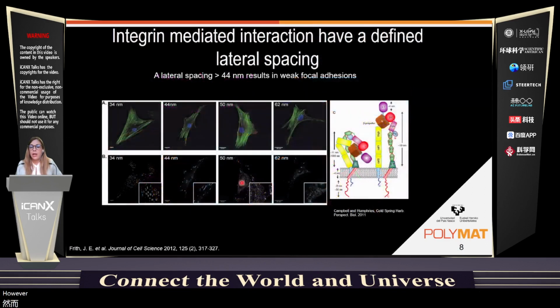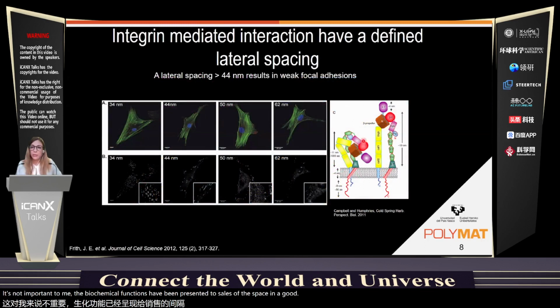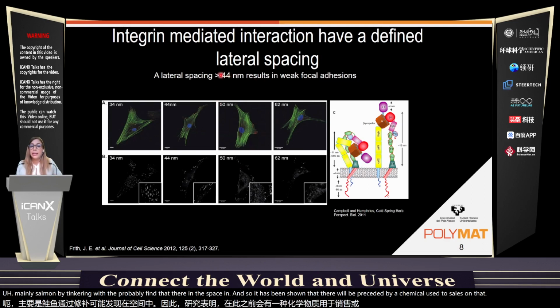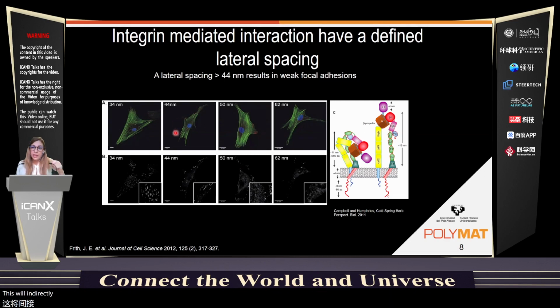However, here it's not only the biochemical functions that we present to cells that are important, but the spacing at which we do it. So these are mainly sensed by integrins that have a defined lateral spacing. And so it has been shown that if we present biochemical cues to cells at a lateral spacing lower than 44 nanometers, this will interact strongly, forming a strong focal adhesion. However, if we have now our biochemical cues a little further apart, these interactions will become weak.